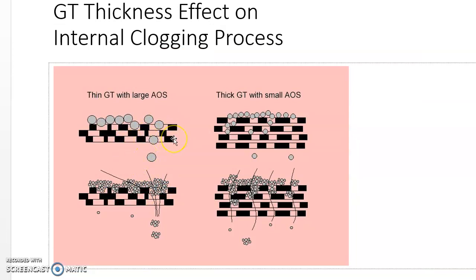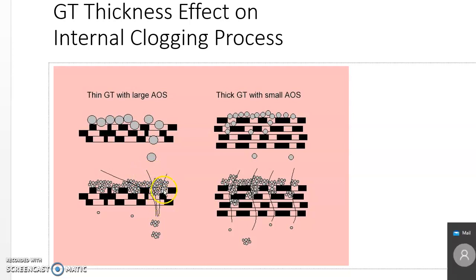This schematic plot compares thin geotextile and thick geotextile in needle-punch geotextile. The thin geotextile, once an upper load is applied, loses the space between the fabric. Thin geotextile also has a larger opening size compared to thick geotextile. For fine particle material — especially tailing material and high fine content — under high hydraulic gradient, fine particles can only access a limited open area, which we call plugging. So thin geotextile can possibly produce this type of poor drainage performance compared to thick geotextile.